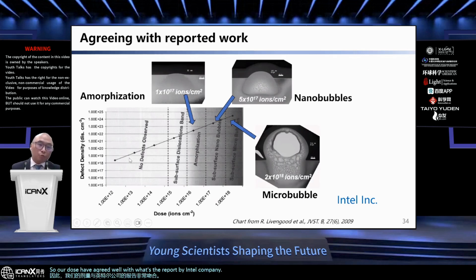Our dose test agrees well with what was reported by Intel. They also reported no defects and subsurface dislocations, similar to here, and a subsurface nanobubble. They also reported subsurface microbubbles. I think we are one step forward: we have microbubbles above the surface.